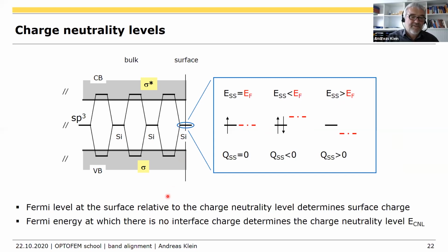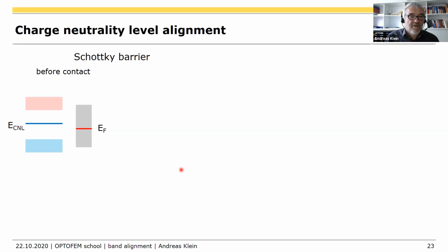Well, in a real semiconductor, you have not only 1 bond, they overlap, so they broaden, the density of states is broadening, but this is a minor detail. It's just to tell you that such a distribution of surface states has a charge neutrality level, and it means that the average occupation of these levels gives us a 0 surface charge. Okay, that's a charge neutrality level. That was for a surface. For the interface, it's a little bit different, but just to give you one rough idea what a charge neutrality level is. So if you have Fermi level pinning, the energy band alignment is the alignment of the charge neutrality levels.